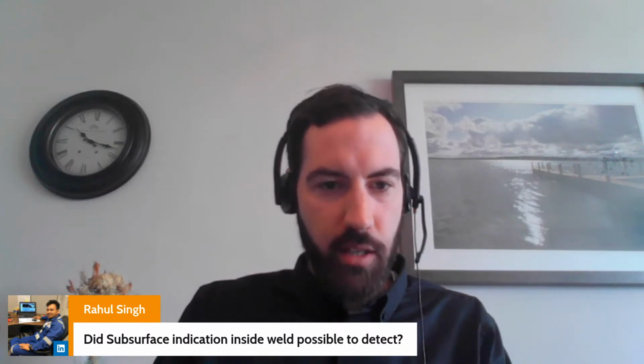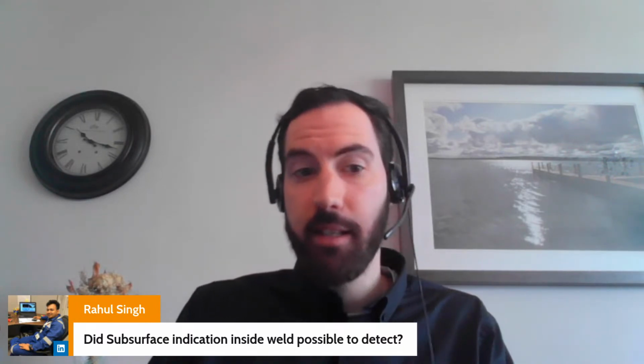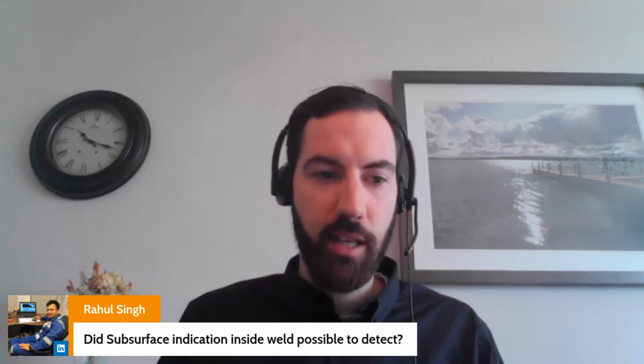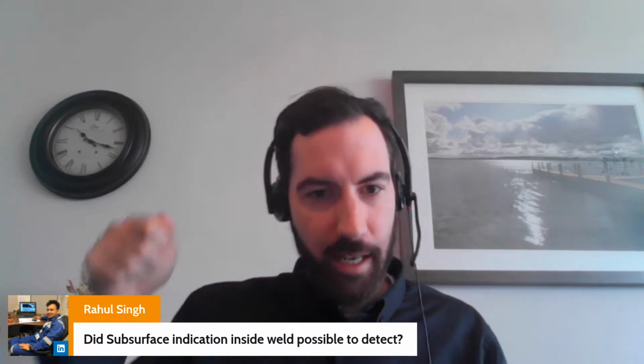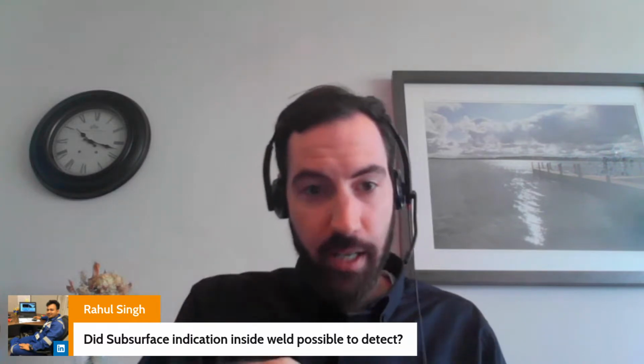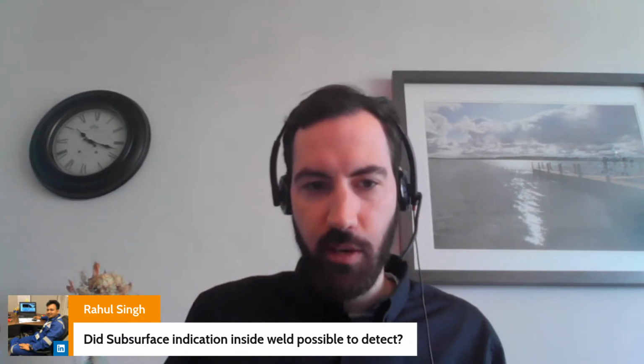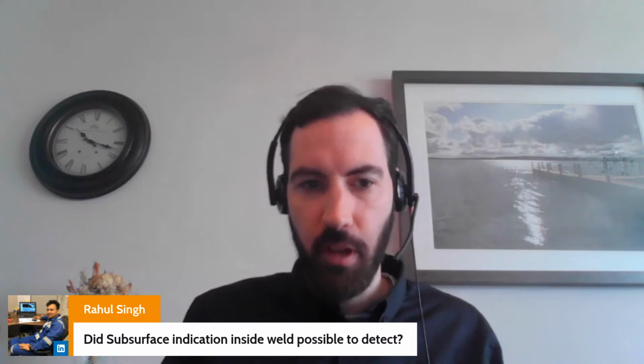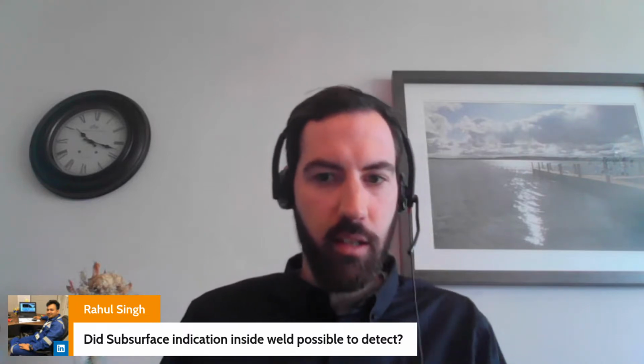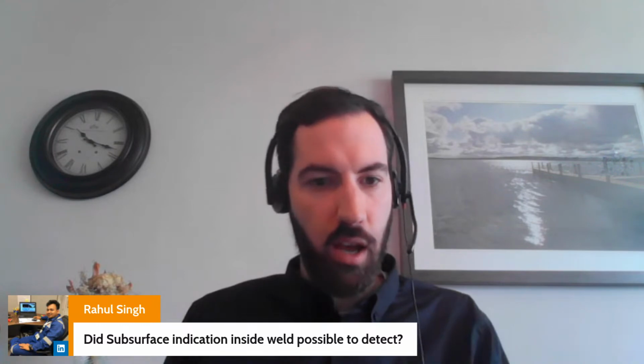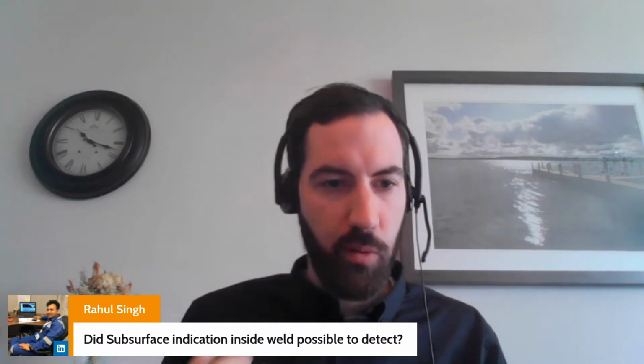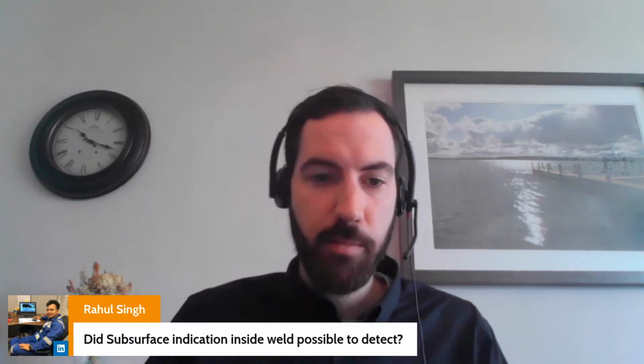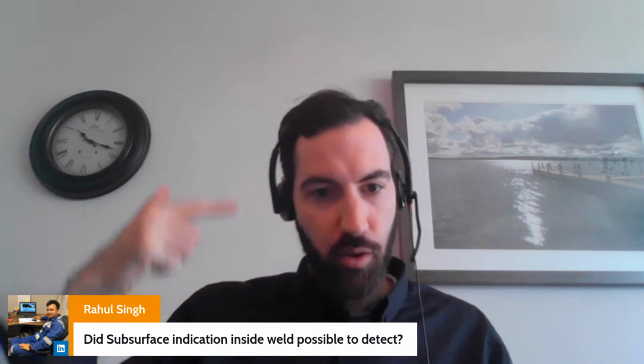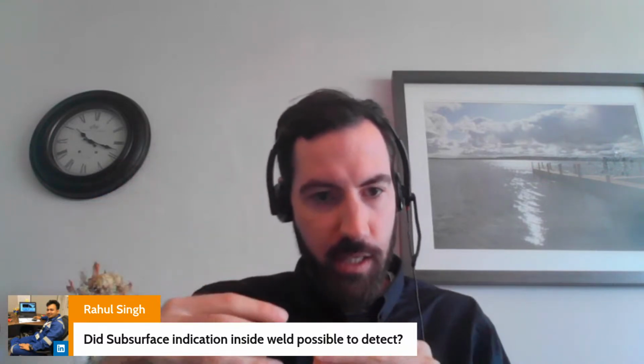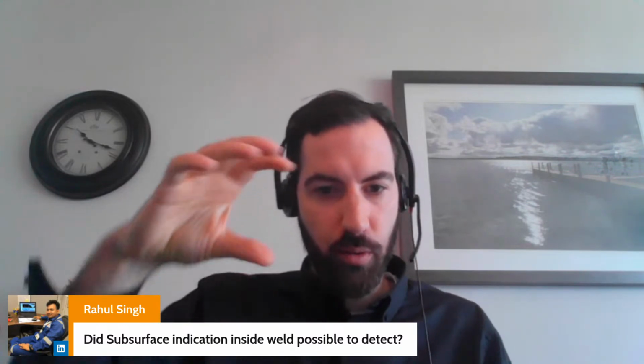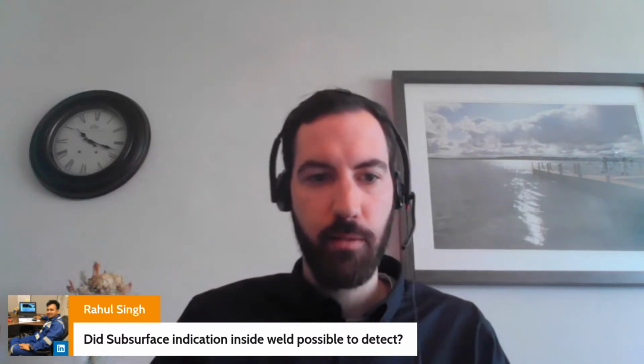Are subsurface indications inside welds possible to detect? Yes, again, it depends on if the weld is magnetic. If you put a magnet on the weld and you can attract it, it means it's like carbon steel, there will be no penetration, not possible. If it's stainless steel, the weld is not magnetic, yes, we can definitely penetrate the weld, and we have done this kind of projects many times where we inspect circumferential welds in two stainless steel pipes. We have this scanner that goes around, and you can detect internal weld flaws, no problem.